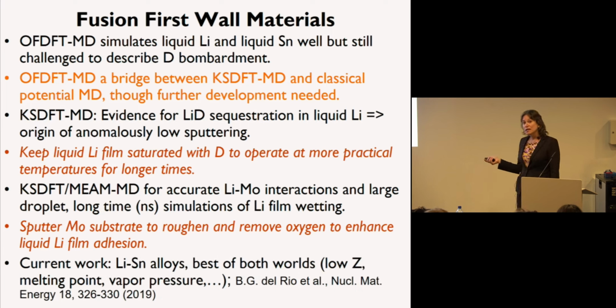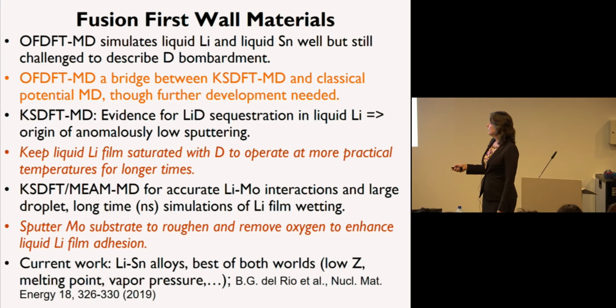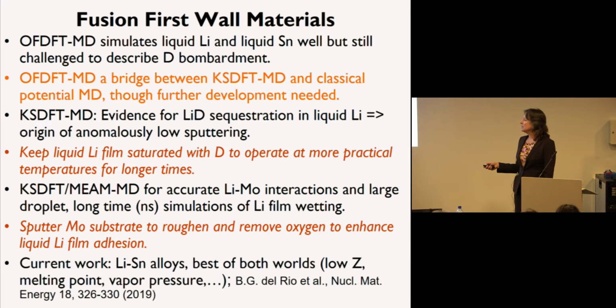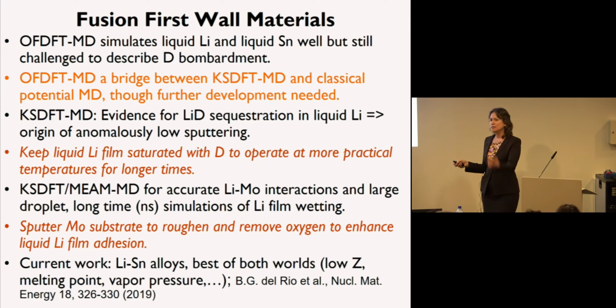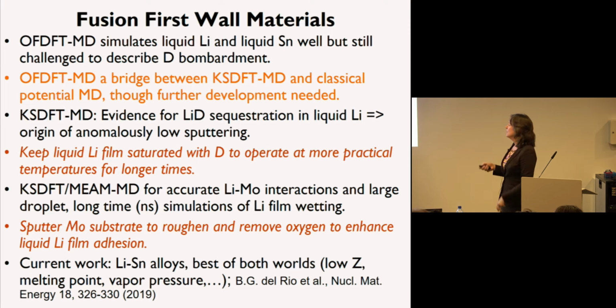So currently what we're working on, and there's one preliminary paper that just came out, is lithium tin alloys. There's a lot of interest in that because it could be the best of both worlds. Turns out we've shown, and we're writing this up now, that lithium segregates to the surface of a liquid lithium tin film. That's good because if you're going to sputter anything, you'd like to sputter something with low atomic number that does the least damage to the plasma. And its overall vapor pressure is low, and we have other evidence that there are other good properties here. So stay tuned for that work.